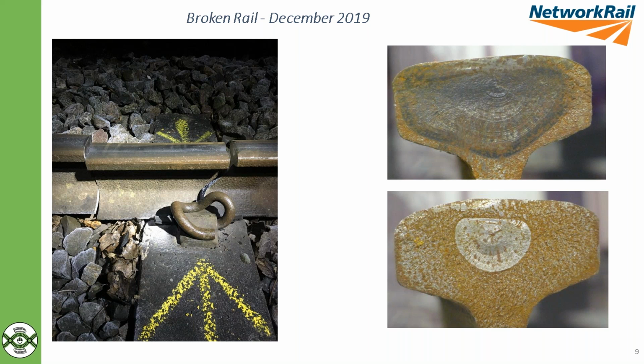And then a secondary break from a much smaller defect, perhaps one that on its own we wouldn't be overly concerned about, but coupled together with an unsupported length of rail, the risk of a secondary break, then the piece of rail coming out. And again, fortuitous that we didn't have a derailment in that situation. But a common theme there with a number of them. It was just some examples. These are ones I would certainly expect to be able to prevent through adequate inspection.